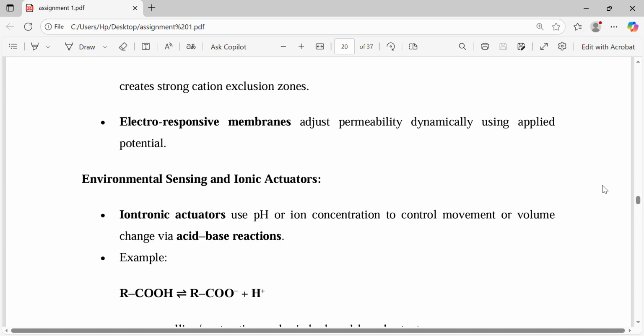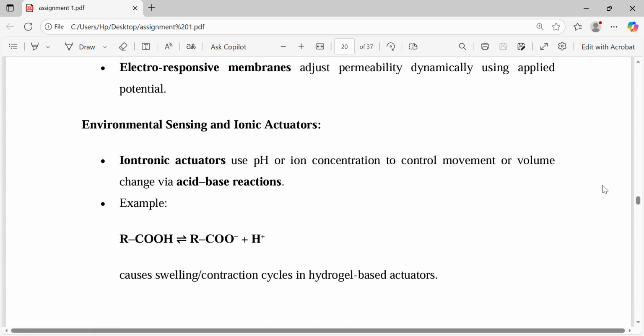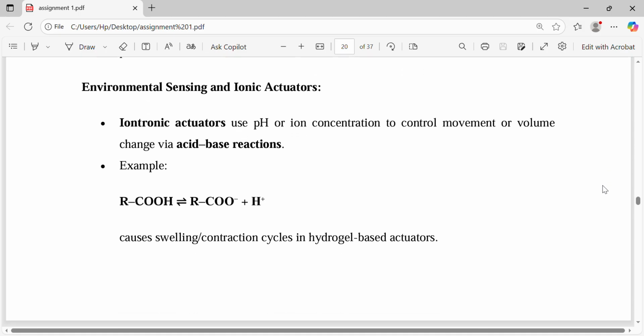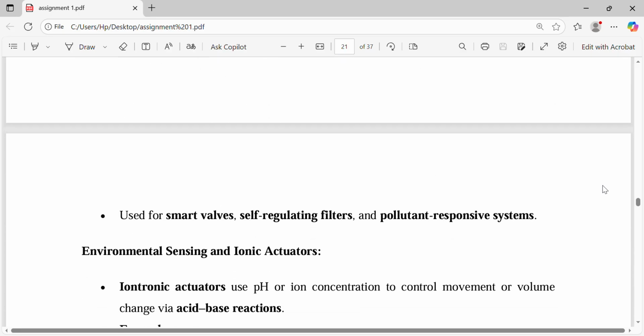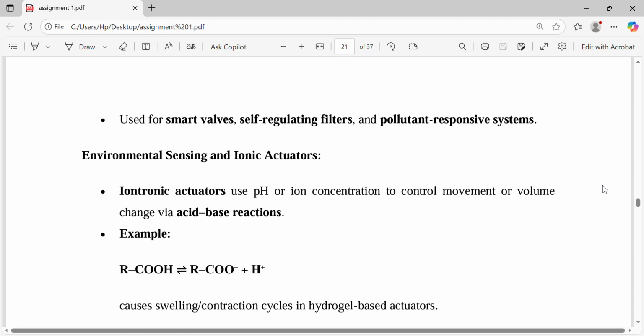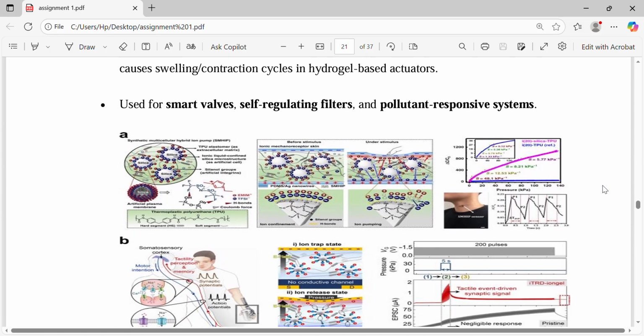Environmental sensing and ionic actuators. Ionic actuators use pH or ion concentration to control movement or volume change via acid-base reactions, causing swelling and contraction cycles in hydrogel-based actuators. Used for smart valves, self-regulating filters, and pollutant-responsive systems.